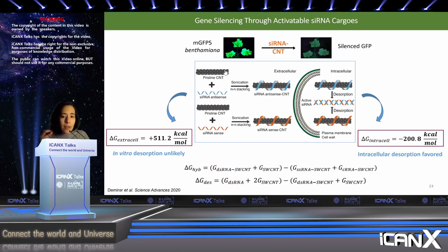So if instead of using electrostatic interactions, we instead use pi-pi stacking interactions to separately load the sense and anti-sense strand of the functional RNA onto two separate carbon nanotubes, we can calculate that these constructs will be stable in the pristine extracellular environment, for example, in a buffer solution, where the preference is going to be for the RNA to remain on the carbon nanotube surface. Once introduced inside the crowded molecular environment of the plant cell, here it would be thermodynamically advantageous for ligand exchange to occur, protein corona formation to occur, and desorption of the siRNA individual strands to an active siRNA duplex, especially if these two strands are complementary to each other, which they are.